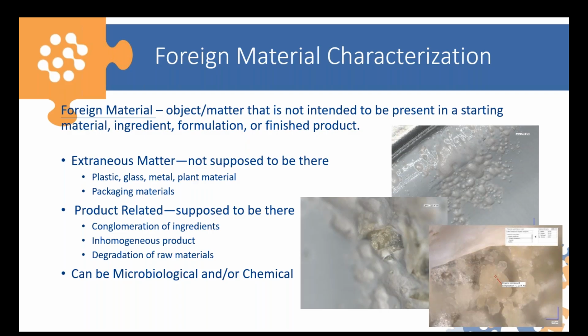So as an example of one of these foreign material characterizations, on the slide, I have pictures of the inside of a can. And what happened here is the customer was producing a canned meat product, and it was canned in a brine. And what they were finding over time and getting complaints about was bubbling or the formation of blisters in the can lining. So you can see here we have a high magnification image of some of those blisters.